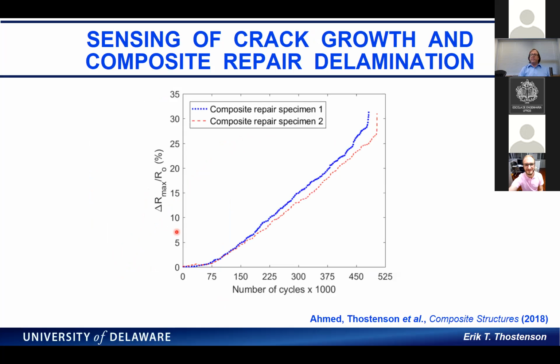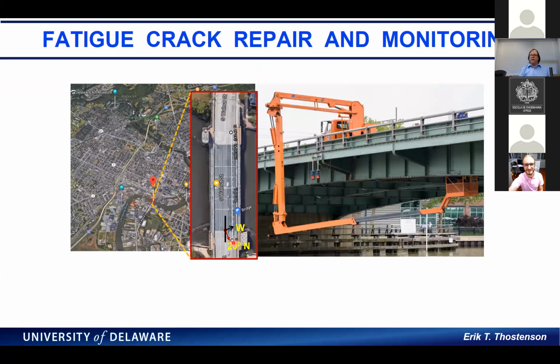And this shows that we're able to detect, and this is with the number of cycles, and it was quite repeatable. And these are a couple of different specimens for the composite repair. But what's more exciting is, once we validate it in the lab, we're putting it on a bridge. And this is in Wilmington, Delaware. This is very close to the train station downtown Wilmington, Delaware.